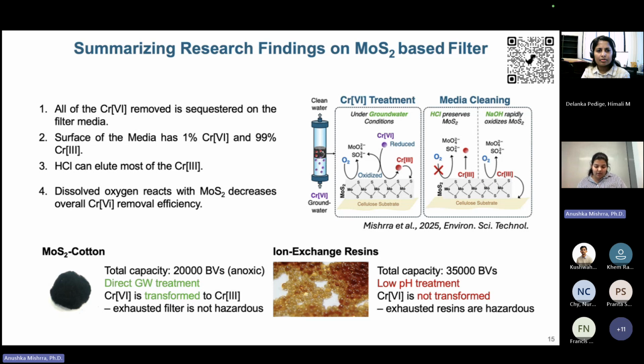And the second advantage that MoS2 cotton has over ion exchange is that the MoS2 cotton can work with groundwater pH conditions which are higher than ion exchange. Ion exchange works at low pH conditions, pH 5.5 and like 6, or maybe a little lower than that. It only performs well at those conditions. At higher groundwater pH conditions, it does not work well.